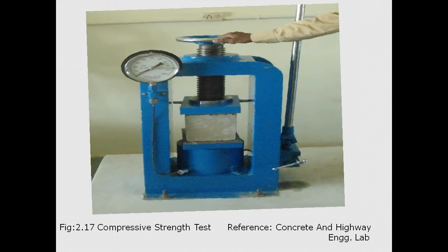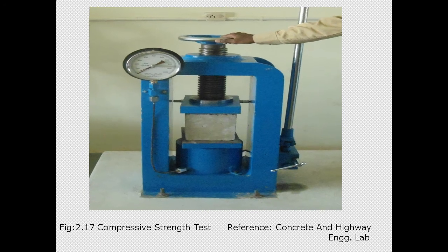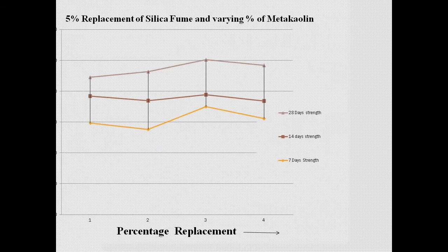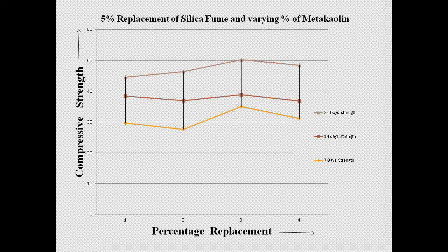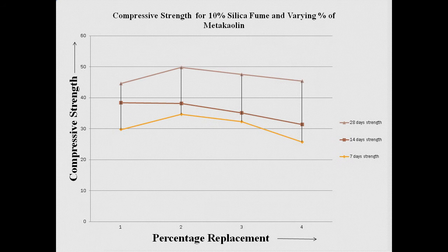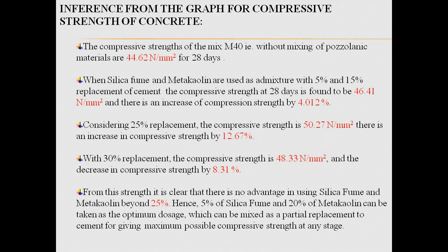And here is our compressive testing machine, where compression of the cube is done. Here is our graph showing 5% replacement with varying percentage of metakaolin. The maximum is obtained on 3, that is the 28-day strength is 50. Then next is the compressive strength for 10% silica fume and varying percentage of metakaolin, where compressive strength and percentage replacement are shown in the graph. This is for 10% and varying percent. And here is the inference from the graph.